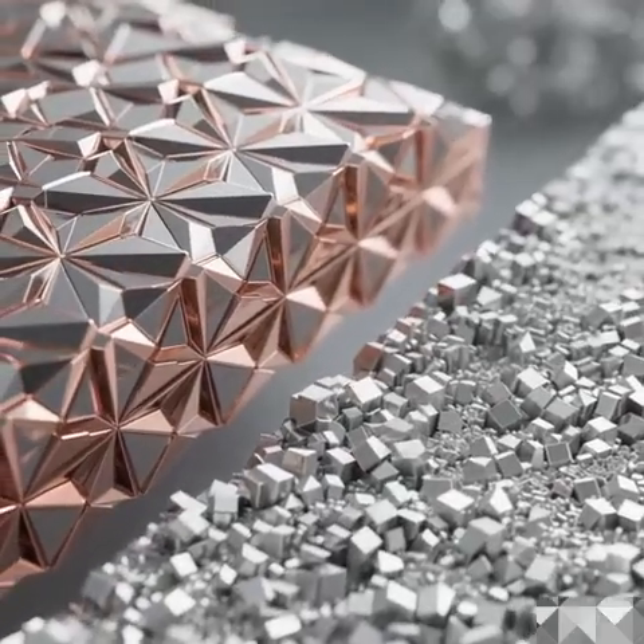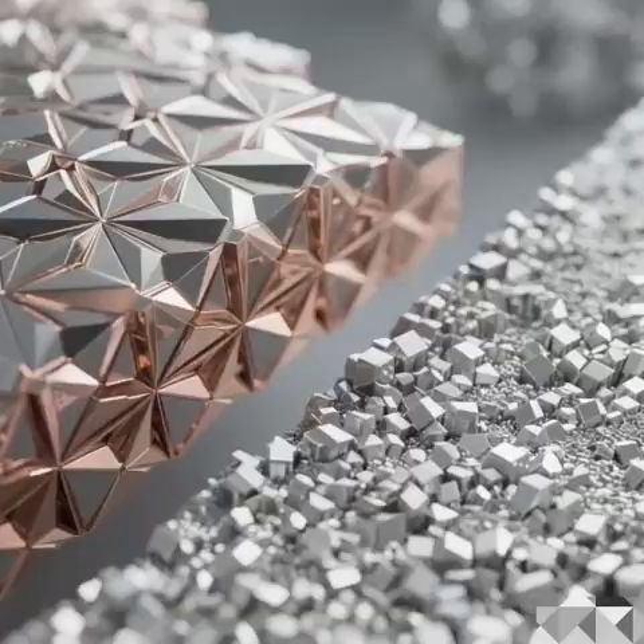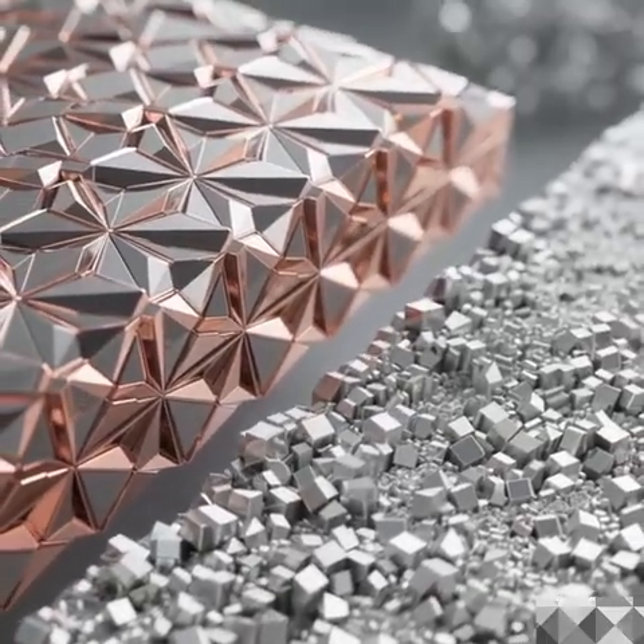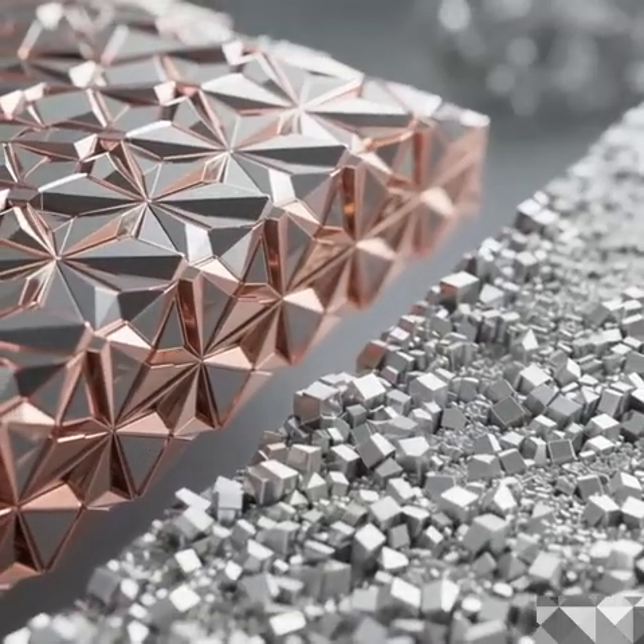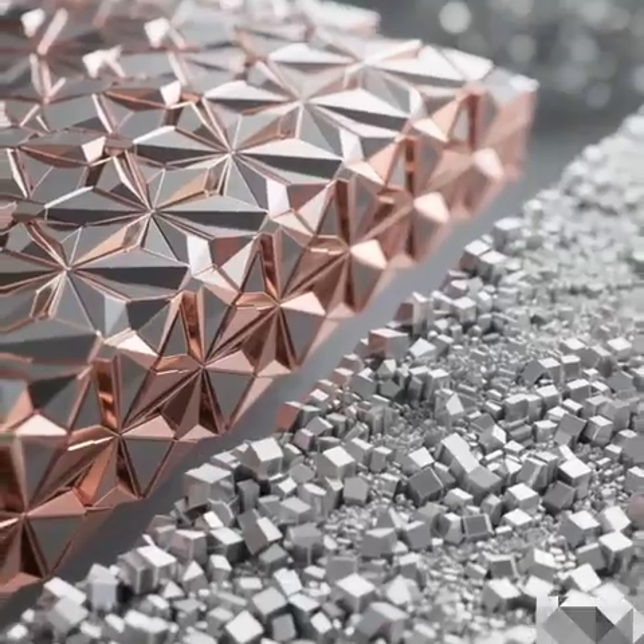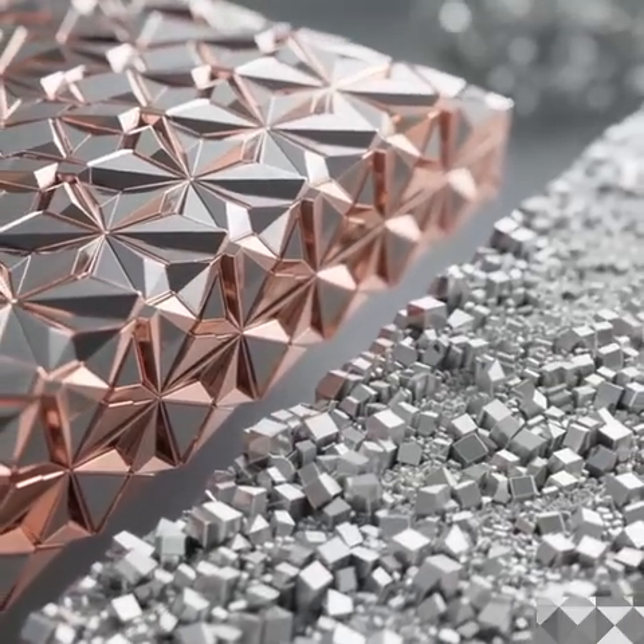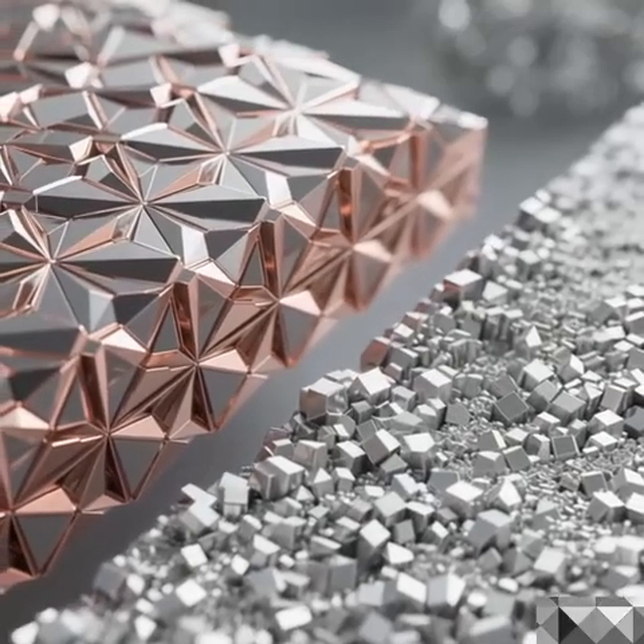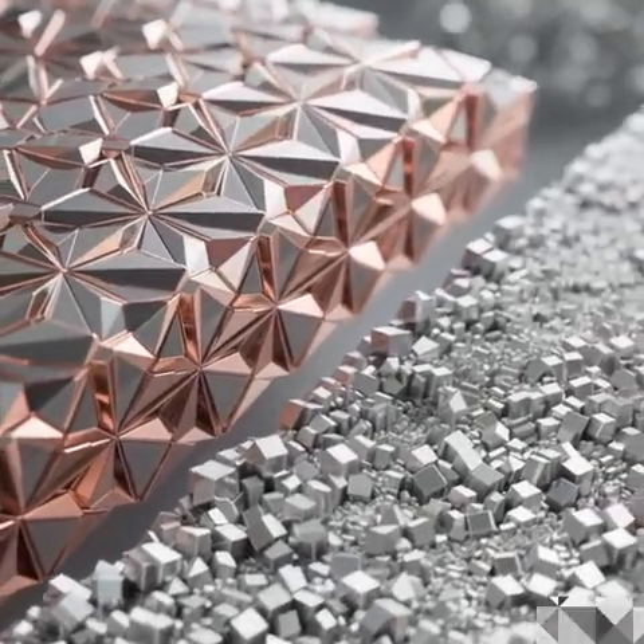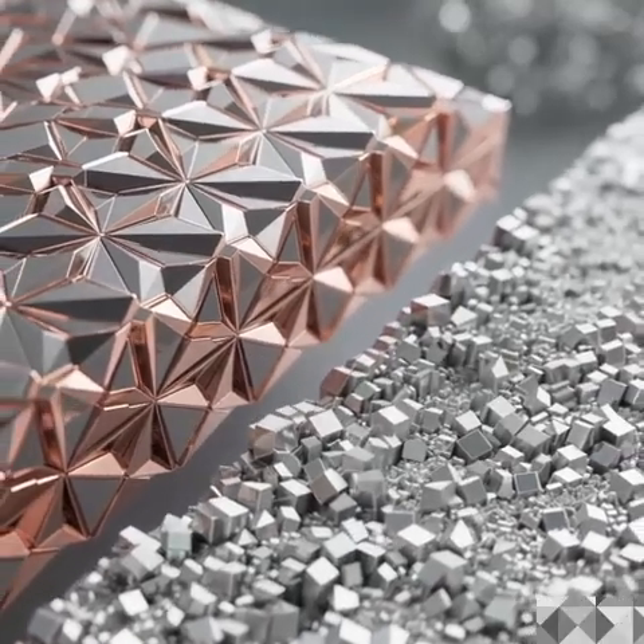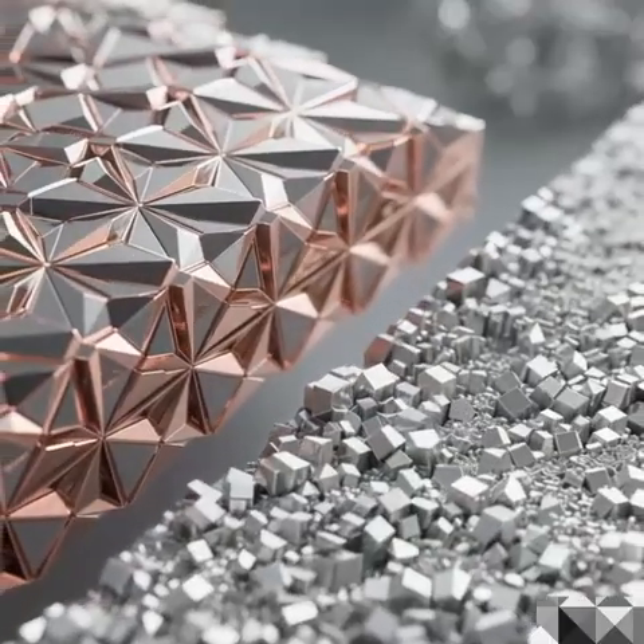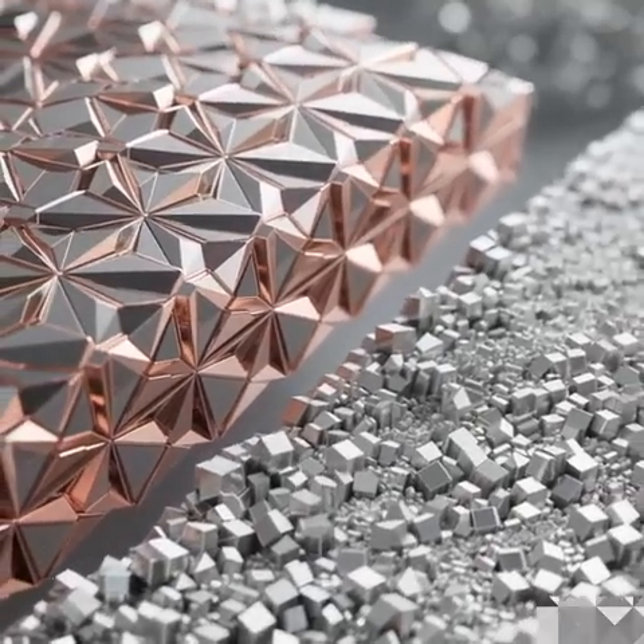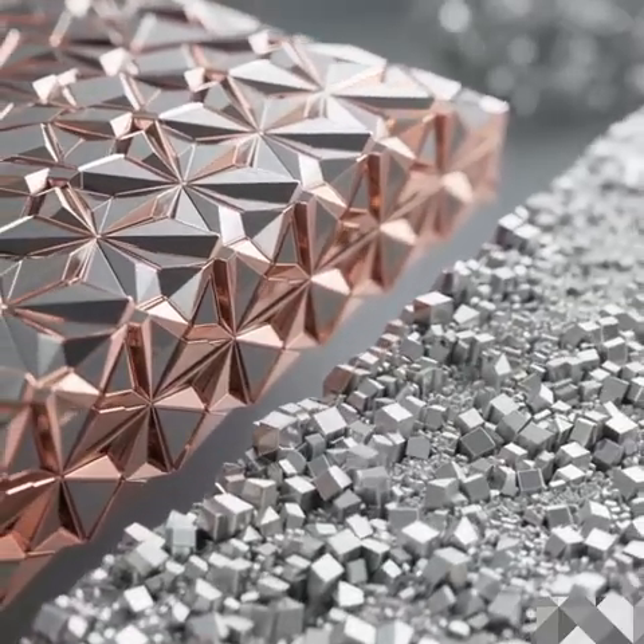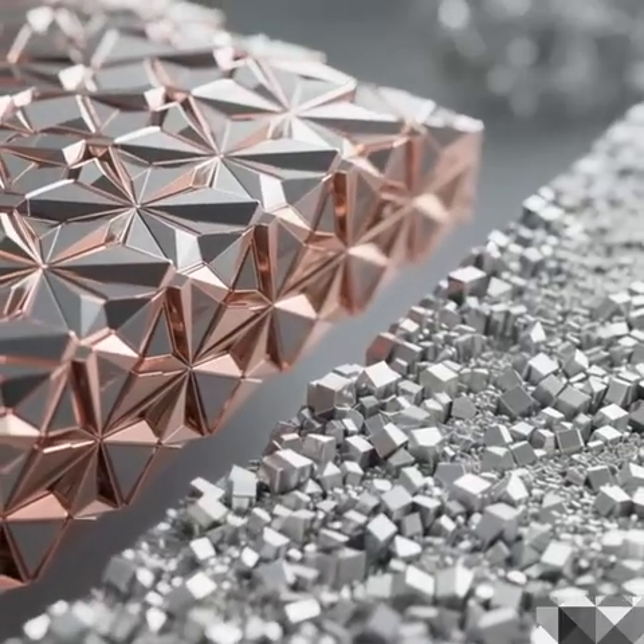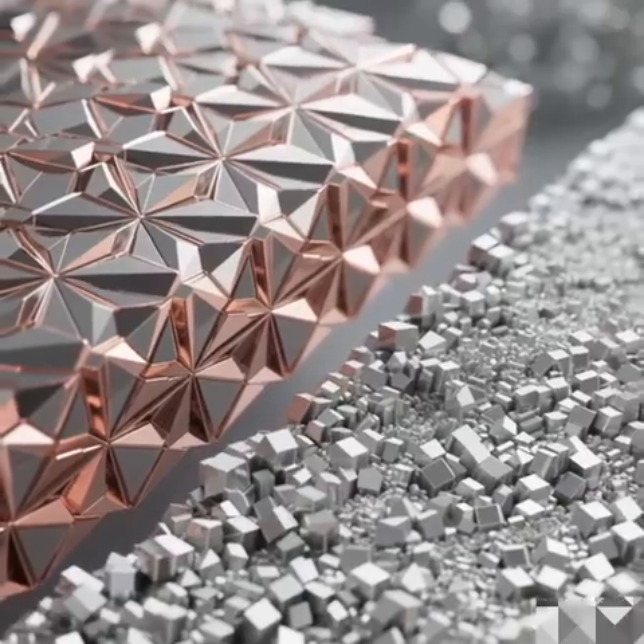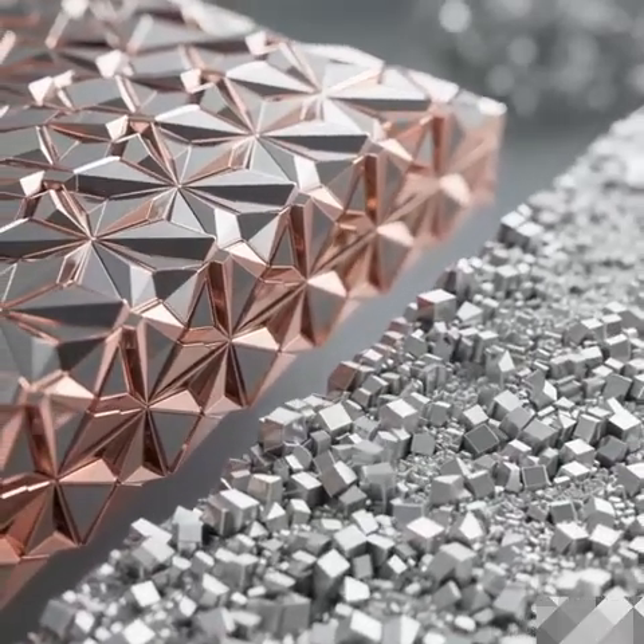And I saw there was recent research confirming this from Hong Kong City University. Yes, work from 2025 has really validated the potential. It's making these complex high-density modules much more feasible to produce at scale. So 2 different coppers, 2 different strategies, but kind of aiming for the same goal. Fundamentally, yes. Both NTU and the NCCG system are all about controlling the microstructure and how the interface evolves during bonding. It's about managing grain growth, grain coalescence, how grains merge together, all at low temperatures. The goal is to eliminate those interface defects, those voids. And clever processing is key for both, like the CMP polishing for NTU and this dual layer design for NCCG. Absolutely critical. It's all about controlling voids and stopping impurities from getting stuck, what's called impurity pinning, which weakens the bond.